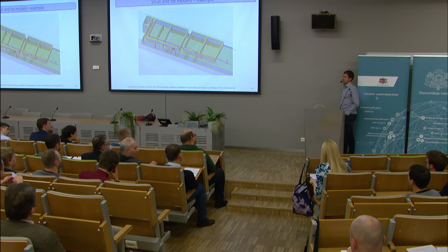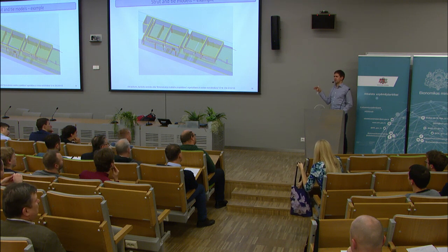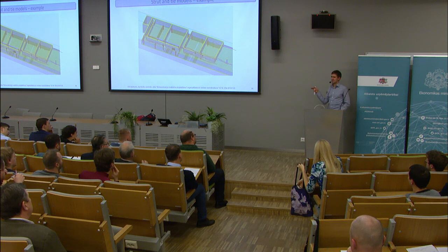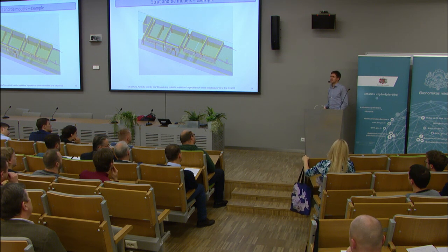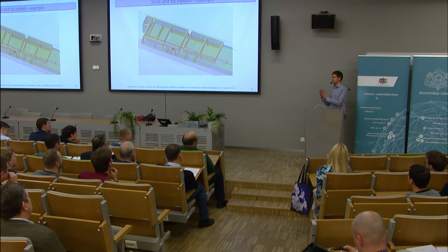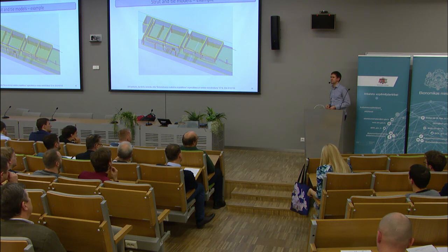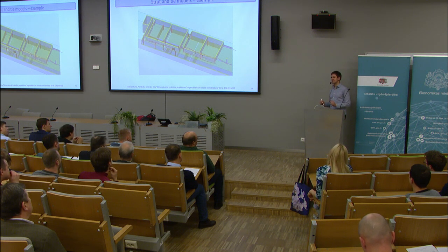I didn't check for the nonlinear creep and shrinkage because the parts where the stress is so high are very small, so they won't have an important influence on the overall behavior. It's basically just below the loading points where the stresses are so high. And I did have enough distributed reinforcement everywhere. These highly loaded elements had reinforcement mesh of diameter 16 every 200 millimeters in both directions to make sure that we do have enough distributed reinforcement for the bottle-shaped struts and that we don't have too wide cracks anywhere.